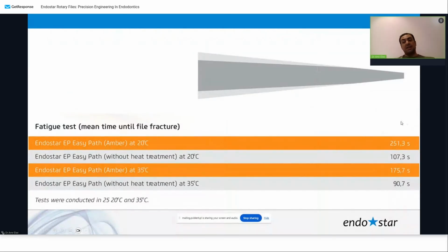But when you understand why, and here, as I said before, temperature. So at 20 degrees, it took 250 seconds under stress and overheat to separate the file. And here at 35 degrees, as you can see here, the orange line, which means it's the amber heat treatment, and the gray line with no heat treatment, so you can understand the difference. Here, it took 251 seconds, and here it took 175 seconds at 35 degrees, which is near body temperature. But without the heat treatment at the same temperature, the time is even less than half. So now we understand, as a new step, how the heat treatment reduces the chances of file separation or deformation, which will lead later on to separation.